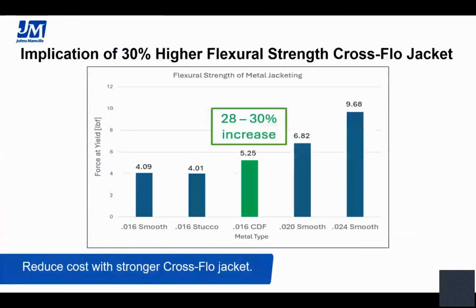All right. Here's our higher flexural strength testing for crossflow. The reason we did this test is a lot of people didn't believe that our 016 crossflow was actually 016 because it feels so much heavier than our smooth and stucco. So we kind of had to prove that it really wasn't 020 in disguise. And it is 28 to 30% higher in flexural strength than 016 smooth and 016 stucco.